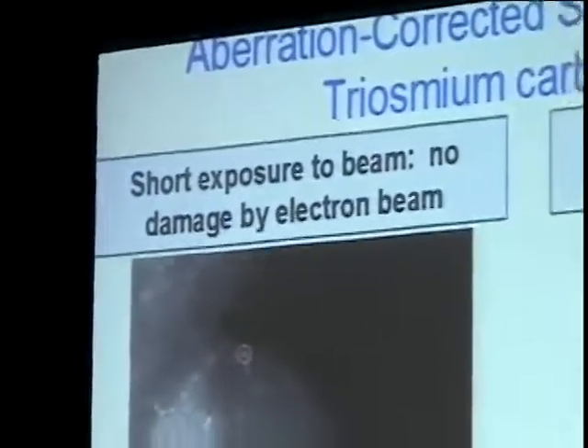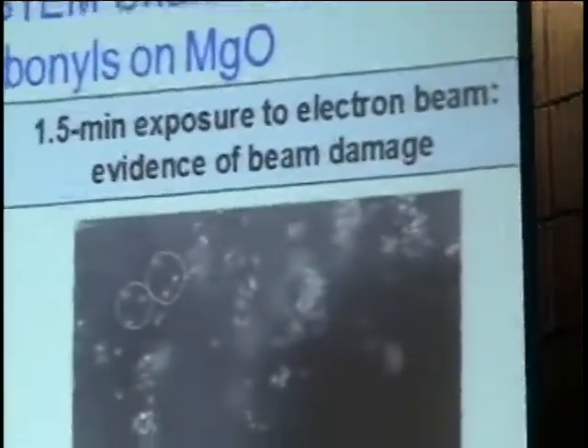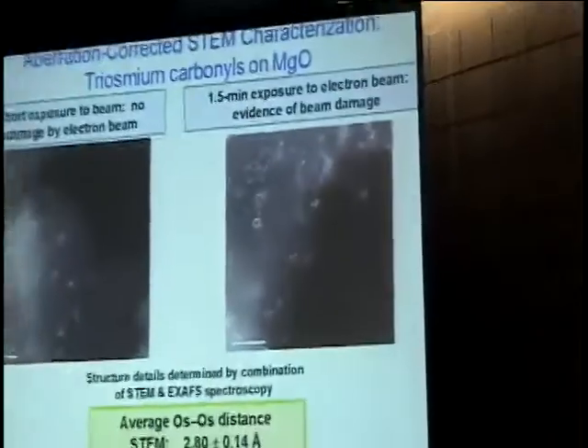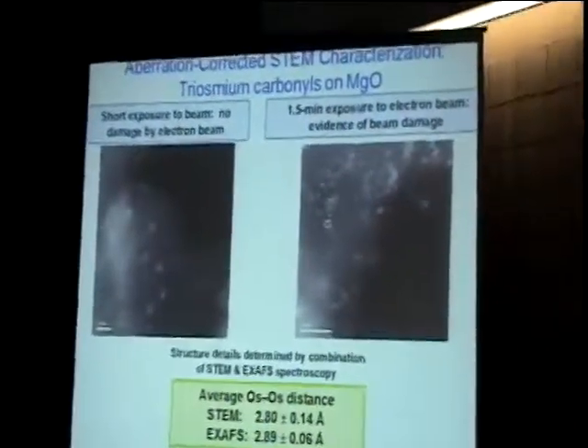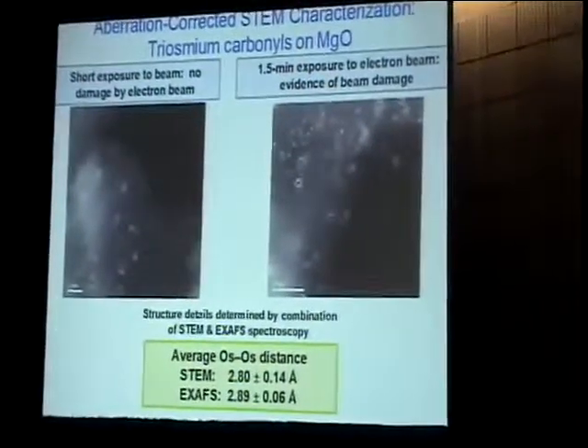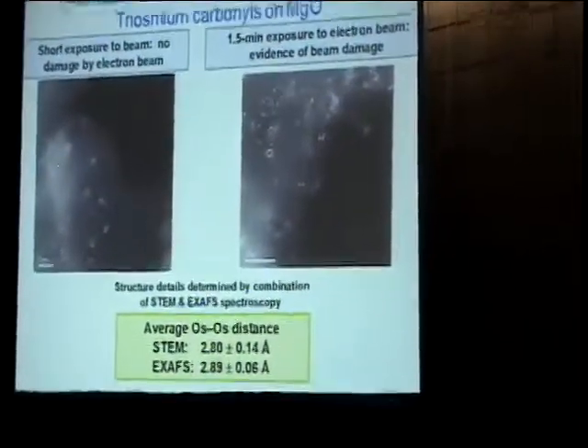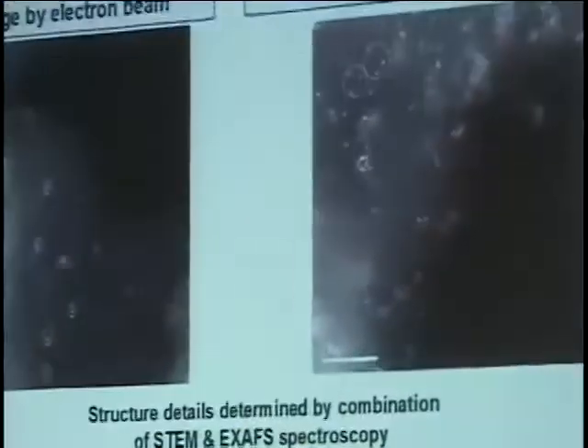So that's a further reassurance, and it's also a demonstration of how much detailed information about supported metals one can determine with this microscopy today. So remember that the triangle of osmiums in triosmium is planar. Now, whether each of those is planar, of course, depends on the orientation of the sample and what face of MgO is in the microscopy. But it's especially advantageous, and of course we're showing some of the best images, to determine a structure of something that's flat, okay, so a triangle.